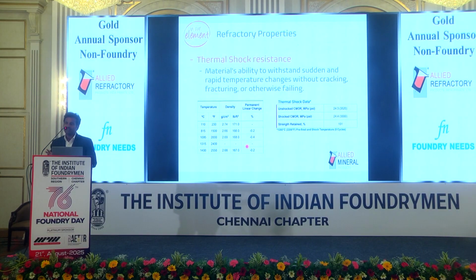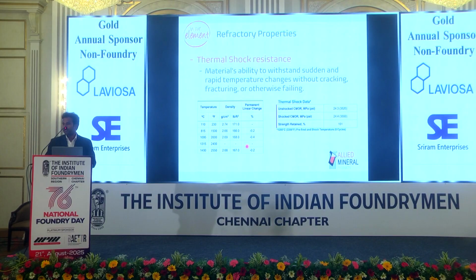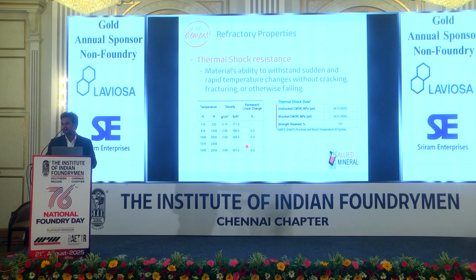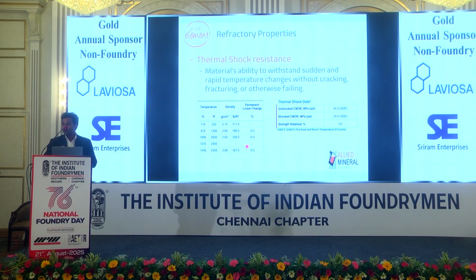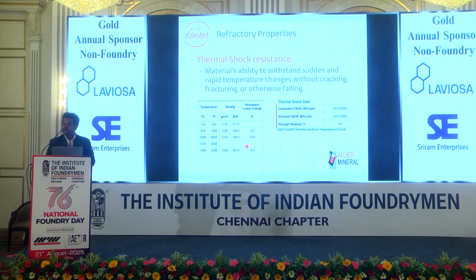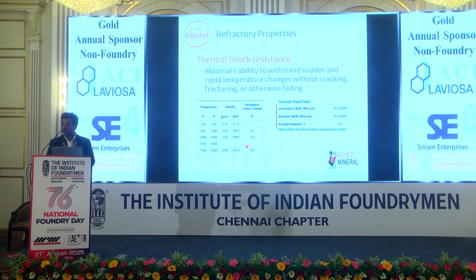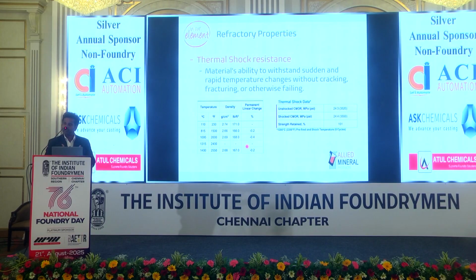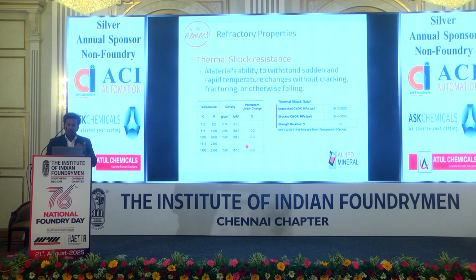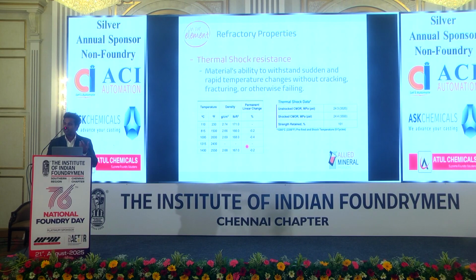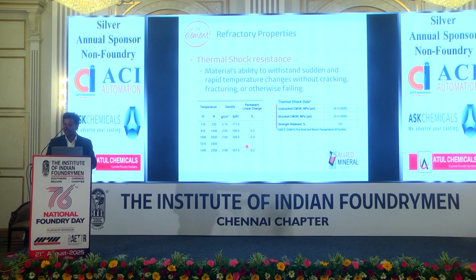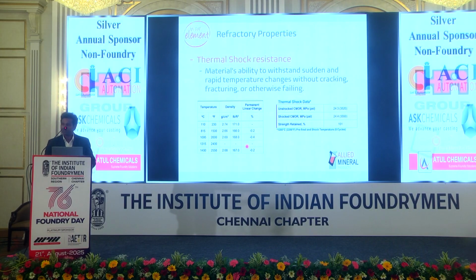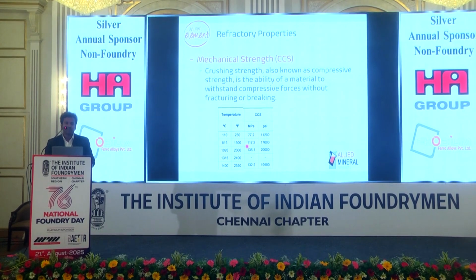Our traditional refractories, like bricks and mortars, basically bricks have many joints, 6 joints. When you do the thermal shocking, there is a chance of these joints opening up and metal can penetrate through the joints. So we need a properly engineered refractory system in the ladles, which can sustain this thermal shock.